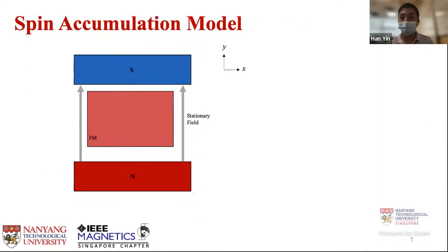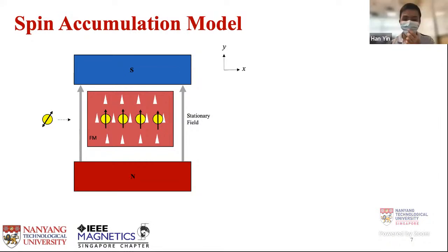Coming back to quantification of spin accumulation, I would like to explain how we quantify spin accumulation using our DC bias harmonic. Here is a cartoon explaining the spin accumulation model. If you have a stationary field pointing up, the FM magnetization will follow the stationary field, in this case pointing up. Now, if you inject a current in the X direction, due to spin Hall effect, the electron spins will be accumulated in the plus Y direction. Here, we can see that the magnetization in FM and electron spin are parallel to each other. Therefore, we can expect to see an increase in Hall voltage.